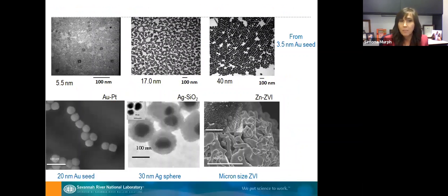What you can see here at the bottom is that we used the gold nanoparticles and started to create these gold-platinum hybrid nanostructures. And of course, we can do a lot of chemistries on these gold and silver nanoparticles. What is really easy to work with is that they have high affinity for thiols. So we always use these bifunctional linkers to functionalize their surface and do additional chemistries. And when we are talking about the seeds, we are also able to grow these nanoparticles on various supports.